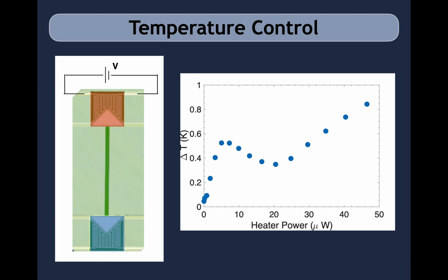To get a temperature gradient across the silicon nitride bridge, as shown on the left of the slide, we can apply power to a joule heater on one of the suspended platforms and measure the change in temperature, or delta T, across the suspended silicon nitride bridge via our deposited FIB thermometers. Due to the geometry and the suspension of the bridge, radiative heating effects are negligible, and we can be confident that the applied heat is mostly directed across the bridge.